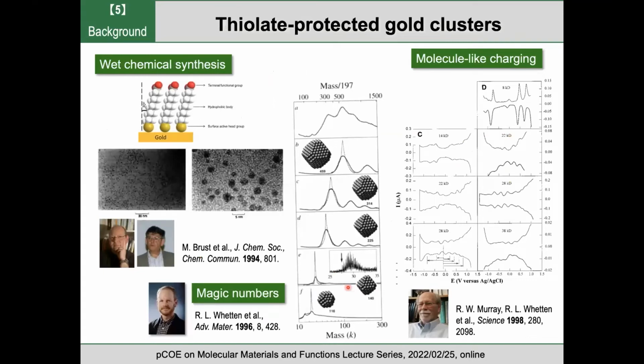And in order to stabilize the clusters against aggregation, we need ligands to prohibit the contact. So as a ligand, thiol has been used as a promising ligand since the first report by Professor Brust and Schiffrin in 1994, because gold-sulfur has a strong affinity. And soon after the first report of the synthesis of gold nanoparticles protected by thiol, Professor Whetten discovered that there are a series of magic species, magic clusters in thiol-protected gold clusters.